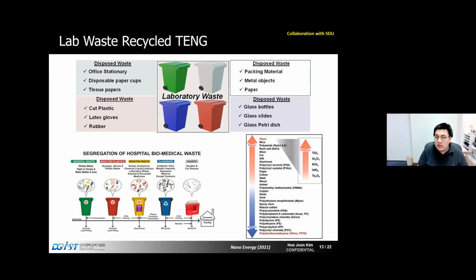So our idea was, why don't we select the right materials and make a good combination of materials and use them to build a triboelectric nanogenerator. If you look here, this is the triboelectric series. The triboelectric effect depends on the surface potential difference between two different materials, because it depends on the electrostatic and triboelectrification effects on the surfaces. So if you select one material as positive as possible and another as negative as possible, when you make contact and separation of those two, you'll get the highest output.